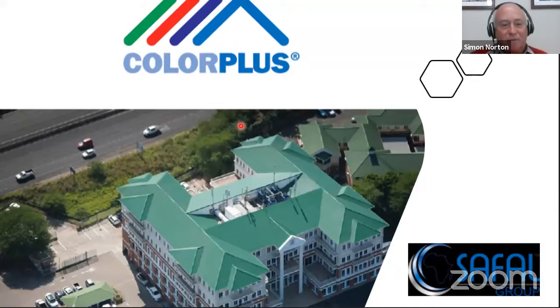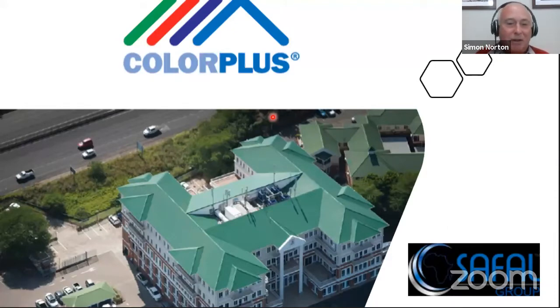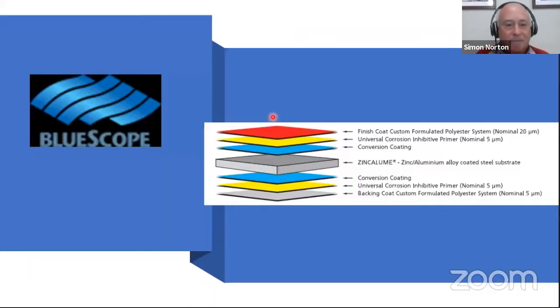Here is an example of the South African manufacturer's Color Plus. This is an alu-zinc coating with an organic coating to give the color, and you can see it's a very attractive and long-lasting material. The way in which it's formulated is there's the zinc aluminium layer. So you've got zinc aluminium on steel, then there's a pre-treatment layer, a corrosion inhibiting primer, and the top coat. And you can choose the top coat. This client has chosen this color, you could choose something else.